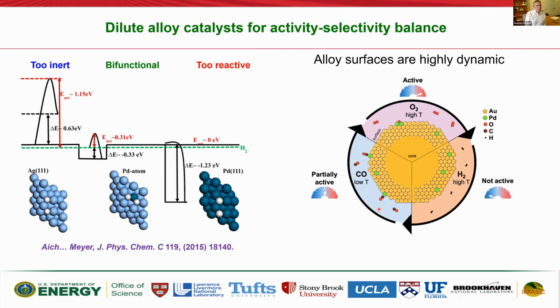And they are successful in many ways to tune activity and selectivity of catalysts. And the biggest part of it is due to this balance that dilute alloys have. When you have, for example, a majority component, like silver 111, it will have very high activation barrier for hydrogen dissociation. And sorry, let me go to another extreme. If you have palladium, not silver, it will have almost no barrier, but very strong binding of hydrogen atoms to the palladium surface. So it's not good either. And if you have palladium dilute on a silver surface or on a gold surface, it will be just right. It will have small barrier and small binding energy. So you can really use it for reaction. And that was shown by Randall Meyer and his co-authors 6 years ago, 7 years ago.